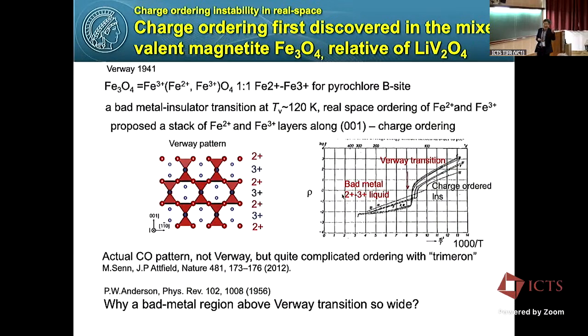Let me begin with charge ordering instability. Charge ordering was first discovered in magnetite, Fe3O4, a one-to-one ratio of iron 2+ and 3+. Verwey proposed that this poor metal to insulator transition around 120 K, called the Verwey transition, is due to charge ordering. He proposed the charge ordering pattern stacking 2+ and 3+ along 0,0,1. But actually, the charge order pattern was found to be not that simple, but quite complicated.